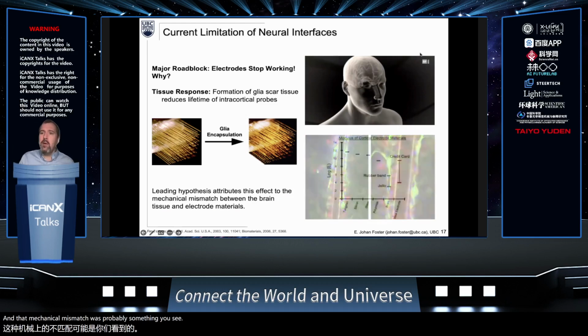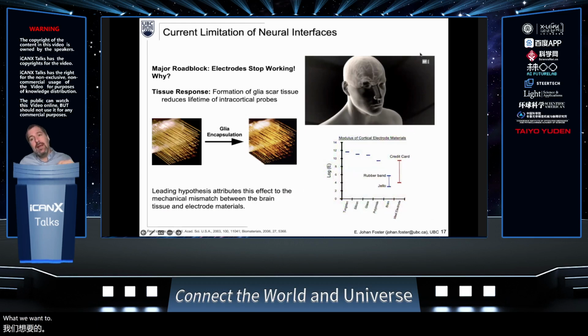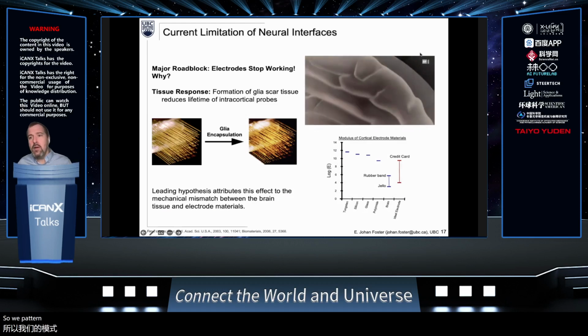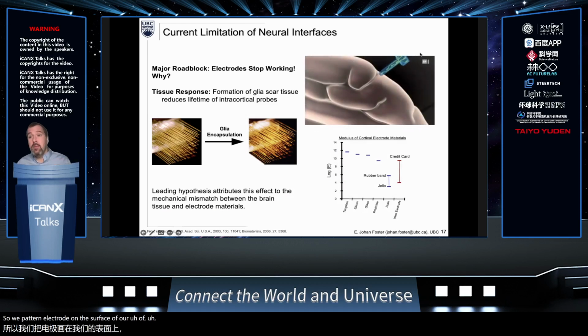So hopefully you see where we're going with this. What we want to do is take a very stiff material. It needs to be very stiff because you need to poke it into the brain. It needs to penetrate the brain tissue. So something that is as stiff as, say, a credit card. And then after you implant it, you don't need it to be stiff. So you want it much, much softer. Okay. So we want that mechanical switching. So we pattern an electrode on the surface of our switchable material. We implant it into the brain, and we see how long we can make this interact with brain tissue.